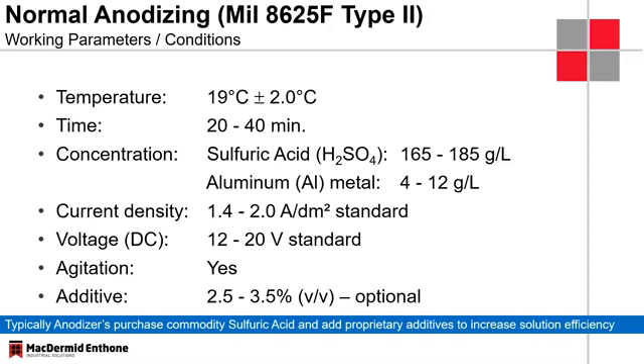Aluminum metal, again, very critical. We have to start with some aluminum, normally around 4 grams per liter, and then once we anodize and we dissolve some of the aluminum oxide layer back into the solution, this aluminum concentration will increase. And around 12 grams per liter, up to 15 grams per liter, we'll see a limit, at which point we have to either dilute our solution or use certain ion exchange technologies to remove aluminum from the anodizing bath.